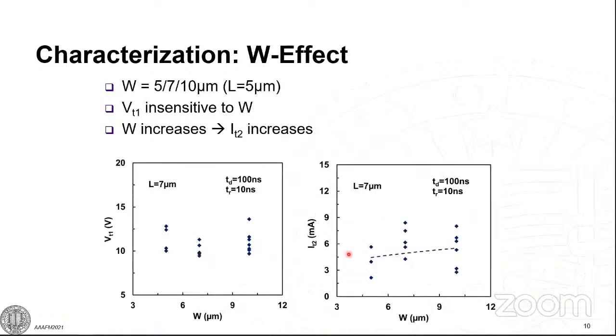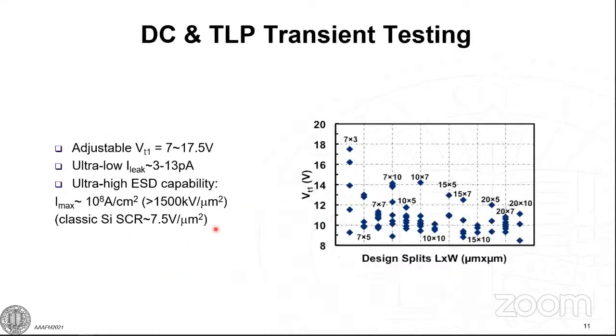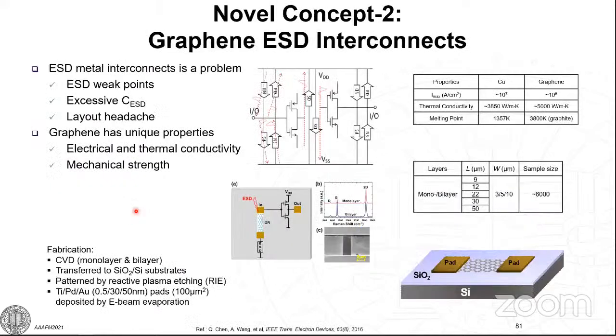Okay, so we also measured the trigger voltage and the current versus the graphene width over there. You can see the difference over here. And one of the key things is you can change the characteristic by changing the device dimension. Say the trigger voltage changes, and it reached probably the highest reported current density, 10 to the 8 amp per centimeter squared, higher than any silicon device. So I'm running out of time.